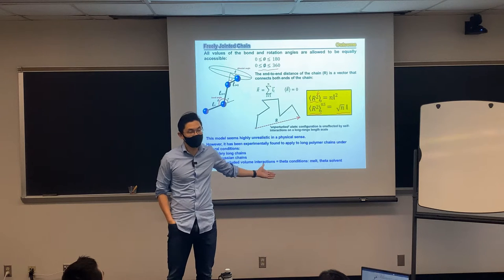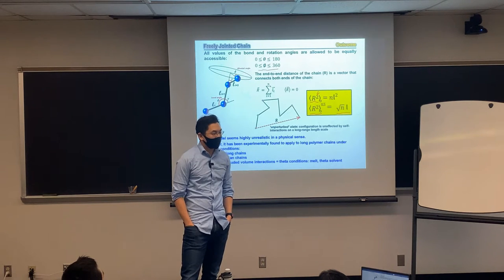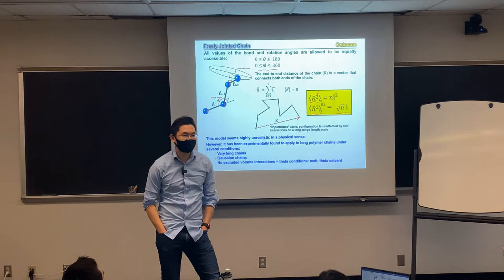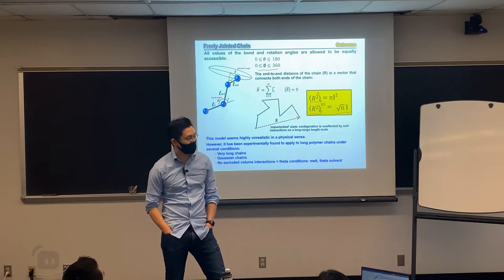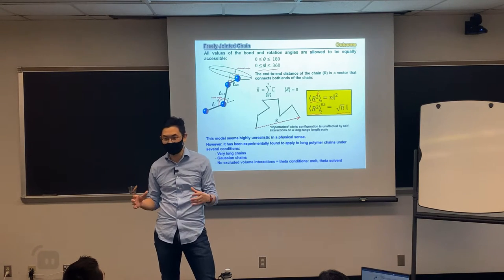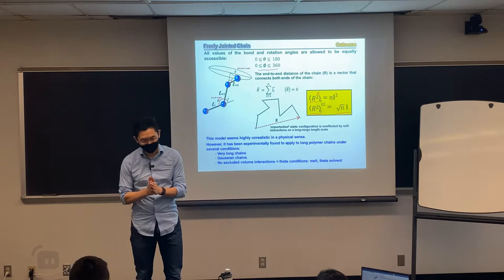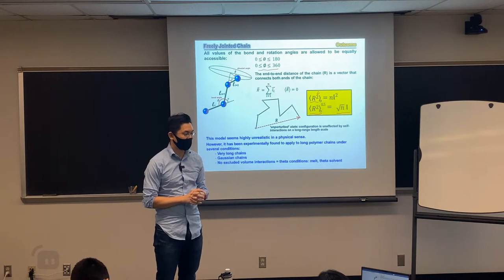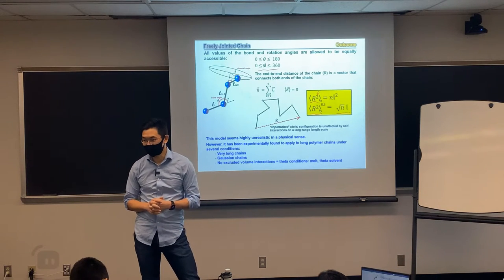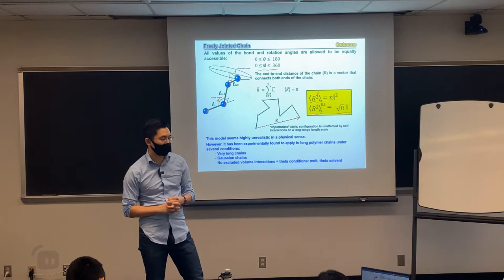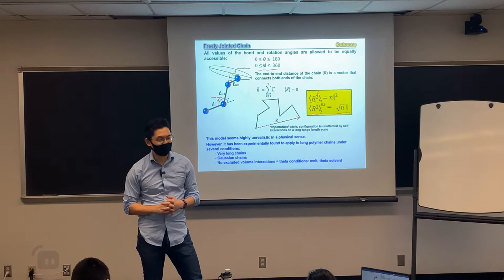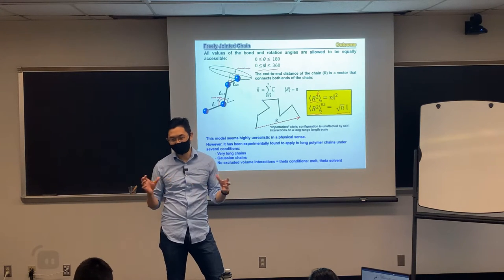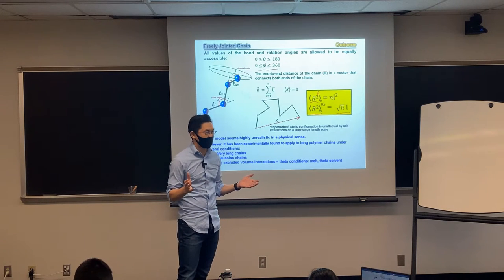In that book, back in the mid 50s, 60s, nobody measured it. He just had a pen and paper working on that. He predicted, he suggested, that in solution, the chain will expand. But in the melt, it will behave like an idealized chain, like a Gaussian coil. Nobody could prove that because no technique was available until many, many years later, when techniques such as neutron scattering and deuterium labeling came into place, and people could actually measure polymer conformation in a melt. They found that's true. That's actually very true. This was not the reason he got the Nobel Prize, but it gives you some insight into how smart that gentleman is.